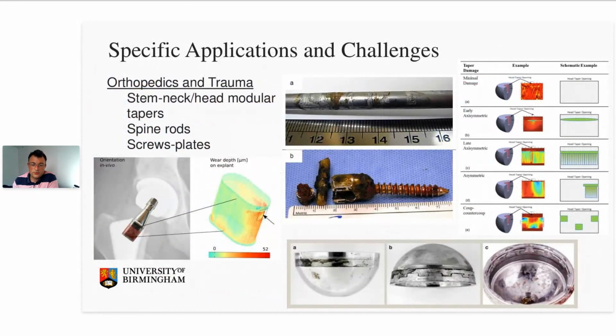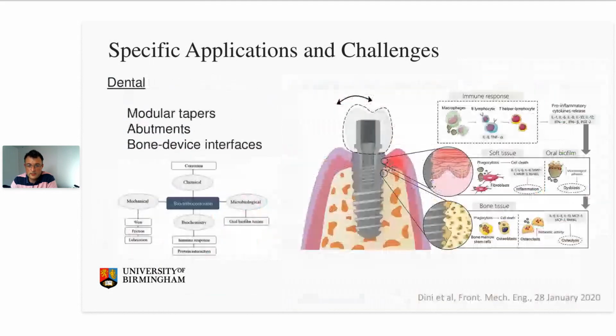So this is a few more examples. Within the MSK domain, it's not just limited to modular tapers. At the head neck, we've also got stem neck interactions where slight variations in materials alloying chemistry were changed, which ultimately led to big changes in the fretting corrosion performance of these materials. But also things like spinal screws, spinal rods, which are typically used to correct adolescent deformities or in the treatment of oncological activities. Corrosion is quite dominant in those domains as well. So there are some huge potentials for device development as well as testing developments within this domain.